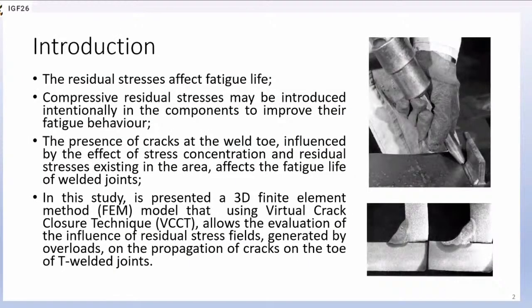The residual stresses affect fatigue life. Compressive residual stresses may be introduced intentionally in components to improve their fatigue behavior. The presence of cracks at the weld toe, influenced by the effects of stress concentration and residual stresses existing in the area, affects the fatigue life of welded joints. The study presents a three-dimensional finite element model that, using the virtual crack closure technique, allows the evaluation of the influence of residual stress fields generated by overloads on the propagation of cracks on the toe of T-welded joints.